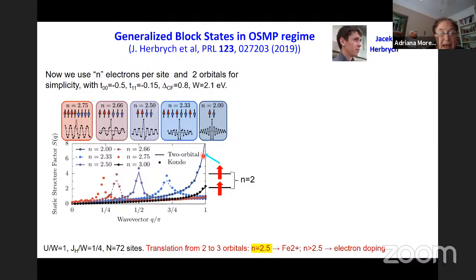As we start adding electrons, the peak moves away from pi, so incommensurability develops, and we start observing these behaviors in the localized spins. At 2.5, which would be the parent compound, we get the peak at pi over 2, and size-2 blocks. But as we add more electrons, at 2.66 we get 3-spin block structures, and at 2.75 we get 4-spin block structures.